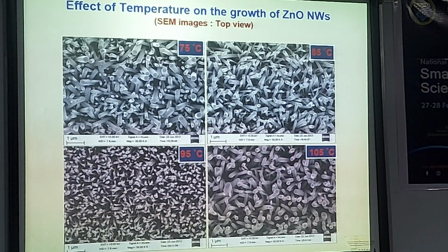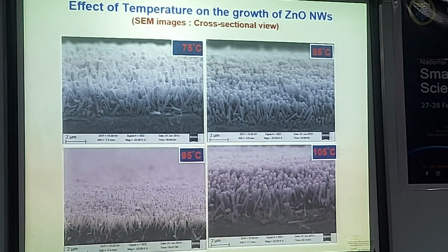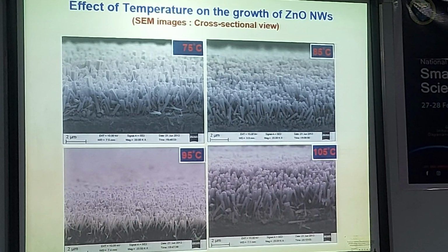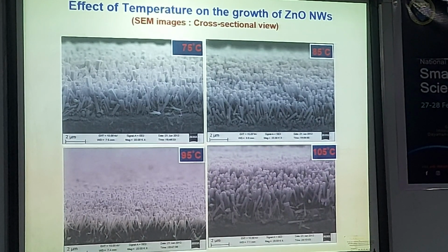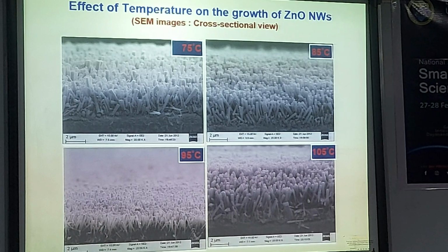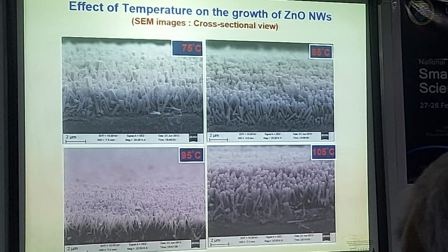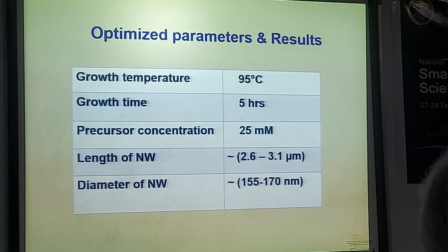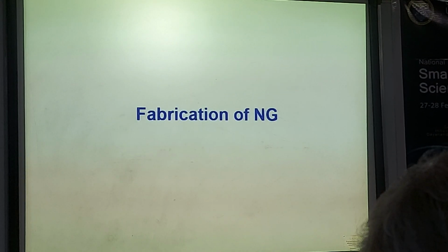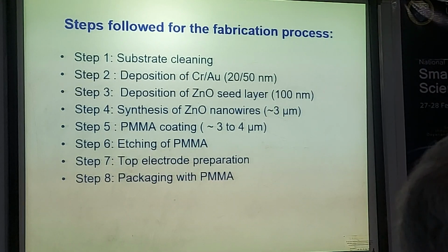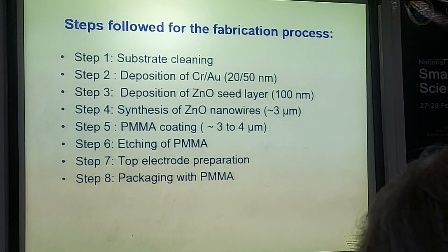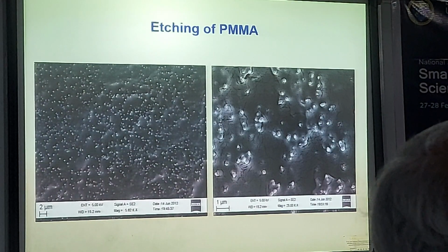And these are the electron microscopy pictures, top and side views of the zinc oxide nanorods that we could synthesize. Some more data on the size and length of the nanorods from electron microscopy pictures. There are various parameters we can optimize to get the required size of the zinc oxide nanorods. So these are some of the optimized parameters. We analyzed using XRD, and we have used these zinc oxide nanorods to fabricate a generator.